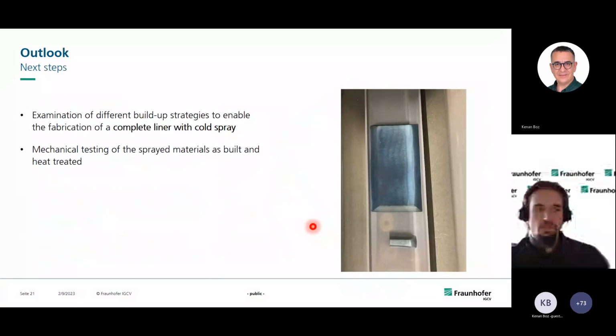Yeah. Let's have a short outlook. What are the next steps? We want to examine, as I've told you, different build-up strategies to enable the fabrication of a complete liner with cold spray. So at the moment, we are able to build up rectangular edges, so block structures, wall structures, but we need to step that up to be able to build a complete rocket liner. And at the moment, we are mechanically testing the sprayed materials in the as-built stage, as well as in a heat-treated stage. And you can see it on the right side here. We got one of our blocks of alloy 718 heat-treated within our vacuum oven.